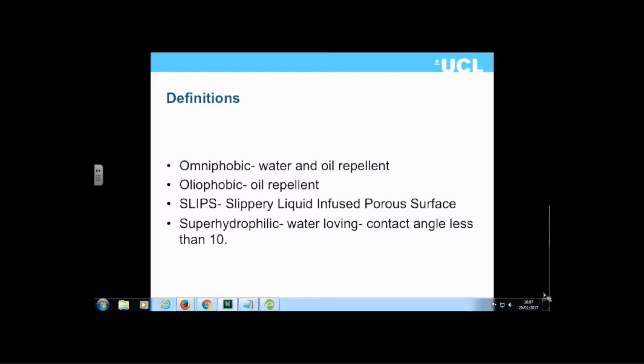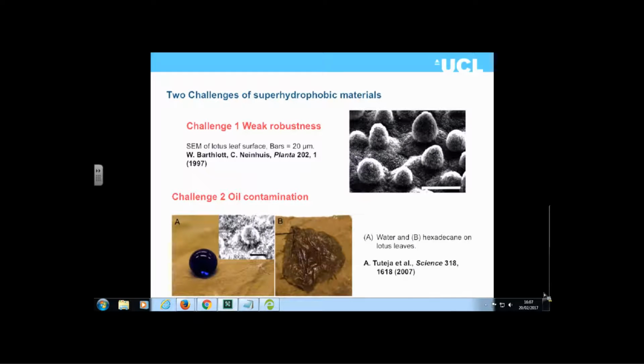Now, for superhydrophobic materials, the commercialization of that has been relatively limited. And the reason why it's been limited and the major challenges in this area are down to surface robustness. That is, the rough surfaces that you need to generate the superhydrophobic surface are very readily abraded with any mechanical shear force. So for example, the majority of artificial superhydrophobic surfaces, if you were to rub them with a tissue, you would remove the superhydrophobic surface because you will remove this surface roughness microstructure.